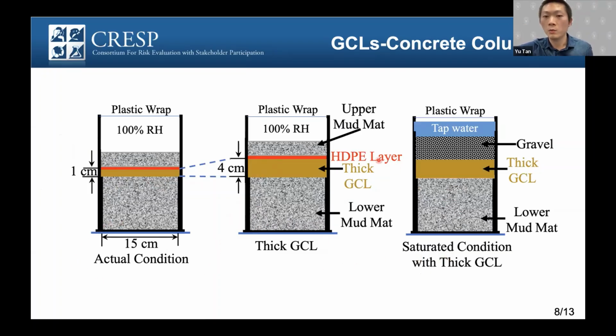And finally, our hypothesis is that the interaction is between the GCL and the lower mud mat, because the HDPE geomembrane will cut off the interaction between the GCL and the upper mud mat. So we take off the upper mud mat and the geomembrane and pour water at the top to accelerate the effect. So this is the worst case in our condition. We call it the saturated condition with thicker GCL.